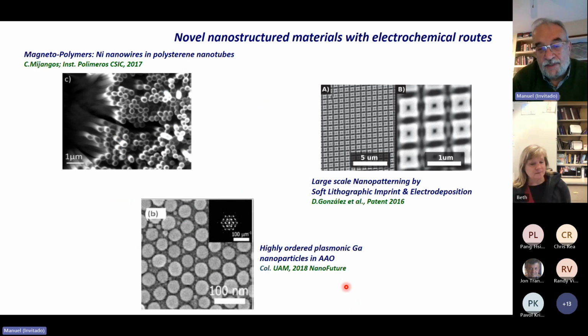Apart from these nanowires, we have been collaborating with other people to prepare other nanostructured materials, playing with the electrochemical route. For example, embedding nickel nanowires in polystyrene nanotubes, profiting from the magnetic and mechanical properties of the polymers. We have also prepared large scale nanopatterning by soft lithographic imprint and electrodeposition, or, in collaboration with professors of the Autonomous University in Madrid, highly ordered plasmonic gallium nanoparticles in the upper part of the pores in the alumina membranes.